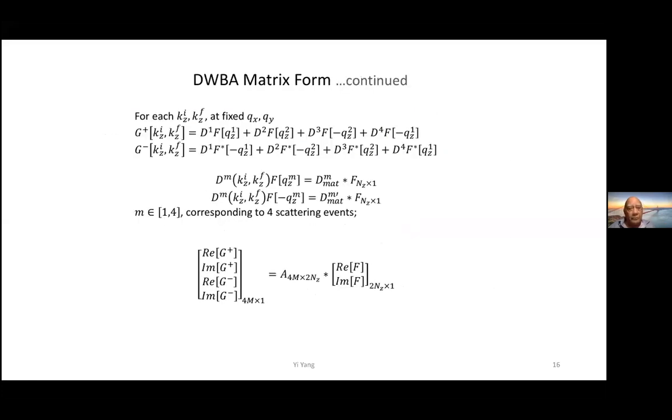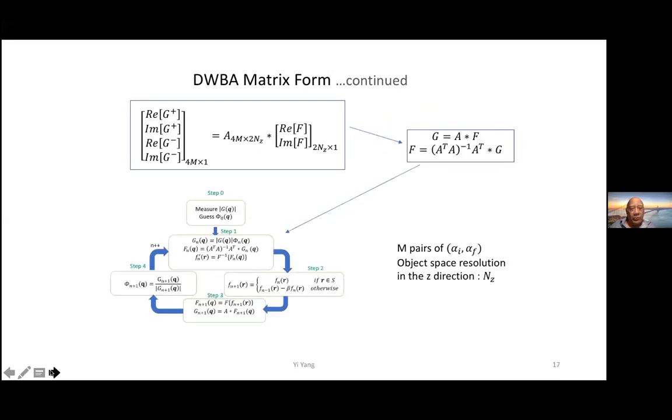And one of the things that you do is you use Friedel's law, which says that when you've got an f of qx, qy, qz, it's the complex conjugate of f of minus qx, minus qy, minus qz. You utilize that in the mathematics too, because that says that the density is real, basically. That's all it says. And then I want to show you some results.